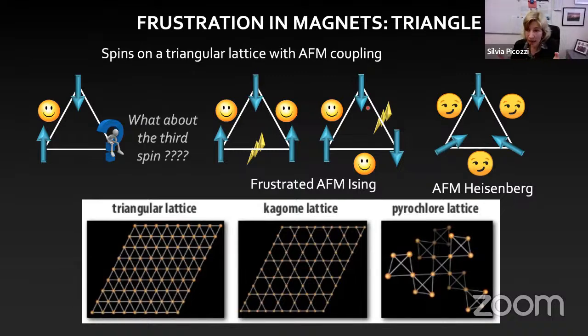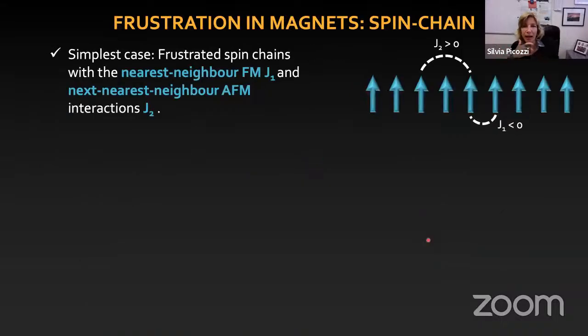So there are certain lattices that are particularly prone to frustration: in two dimensions the Kagome and the triangular lattice, in three dimensions the pyrochlores. And so you can also have frustration in a single chain. It's enough, for example, to have a small first nearest neighbor interaction, which can be ferro or antiferro, but that's small. But if I have a large J2, a large second nearest neighbor interaction, which is antiferromagnetic, then it depends on whether the system has a large anisotropy or small anisotropy.